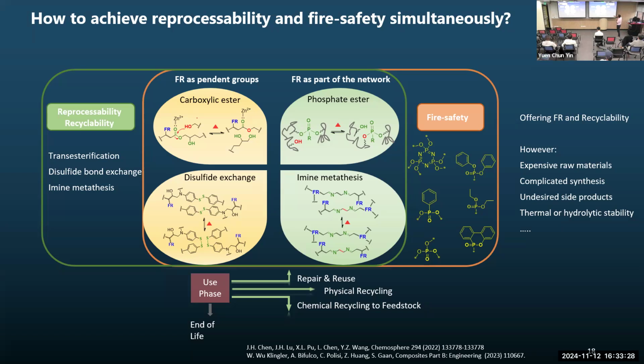People have used phosphorus-based flame retardant. They have used sulfur-based flame retardant. The problem with all these flame retardant strategies or recycling strategies is that a very complicated synthesis process has been used. And in some cases, the fire performance has not been good. But in many cases, it has also been very difficult to achieve good mechanical performance. Okay, so there are a lot of shortcomings of these inherently flame retardant recyclable thermosets.